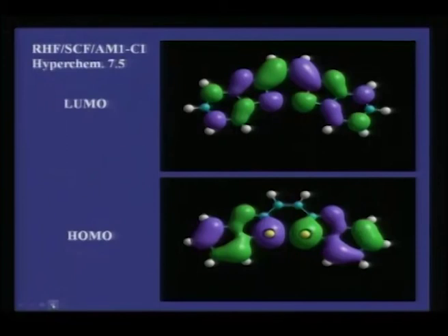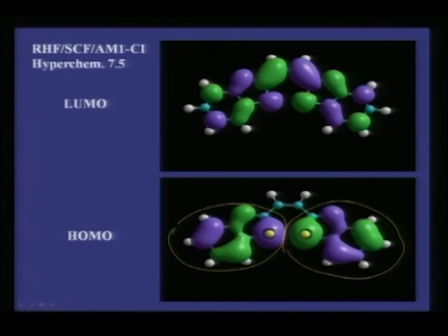Therefore, if you do a semi empirical calculation and look at what really is happening in the case of trans dB, you would see that the HOMO, the highest occupied molecular orbital, electron density mapping shows that the charge resonance is confined only to the benzothiazolyl ring. In the lowest unoccupied molecular orbital, the charge is transferred across the ring through the ethylenic double bond in the excited state.